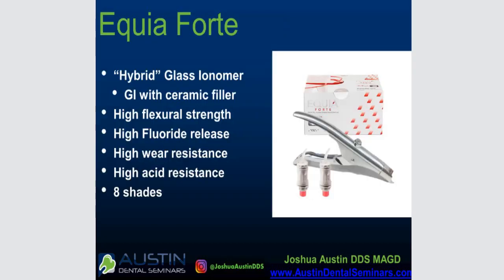So Equia Forte is a little bit different. We talked at the beginning of the webinar tonight about the fluoride material releasing continuum, and that true glass ionomers released and recharged more fluoride than resin modified glass ionomers. And so, if you're looking at fluoride recharge and release as being a real driver to when you're using this, so caries control patients, that kind of stuff, Equia Forte is a great choice because from a fluoride recharge and release standpoint, there's no resin in this material, so it behaves much more like a glass ionomer.